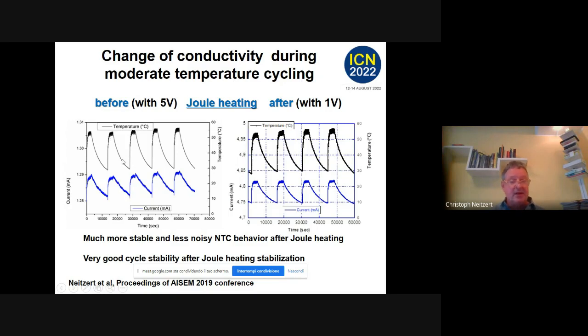This is measured by a thermal element, and this is the current of our sample. We know it has exactly the same temperature in the slow cooling range, not in the heating range. So normally we take data of the slow cooling. Before, we have even some noise and some non-monotonicity, but already almost monotonic behavior, so we could see it is a temperature sensor. After the Joule heating, it becomes much more clear and much less noisy. Here is 1 volt, here 5 volt applied. We have a much higher current, and it's an NTC resistance.